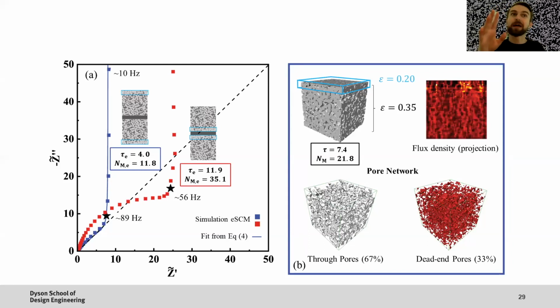But with our method now, where it's how easy it is to get from one surface to the nearest region of active material on a capacitive surface, it really matters a lot. So if you've got a very low porosity region right next to the separator, your impedance is much worse, as you'd expect, as we have actually seen in real batteries, right? And if you've got a quite dense region all the way up at the current collector, but nice and porous before then, great, nice and easy transport, easy to access all the places you want to go.